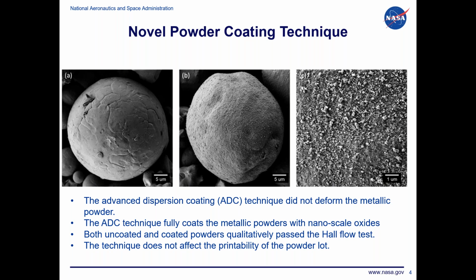What's really nice about this technique is that it is actually amenable to the 3D printing process. Again, when I mentioned ball milling, that heavily deforms your powder, and it really affects the flowability of the powder and your size distribution and things like that. With this coating technique, what we found is that in many instances, it actually improves the flowability of the powder. We've been able to take metal powder that wouldn't flow in our printer, coat it with these nanoscale oxides, and all of a sudden it flowed well enough to actually print with. So coated metal powder feedstock is very amenable to the 3D printing process.